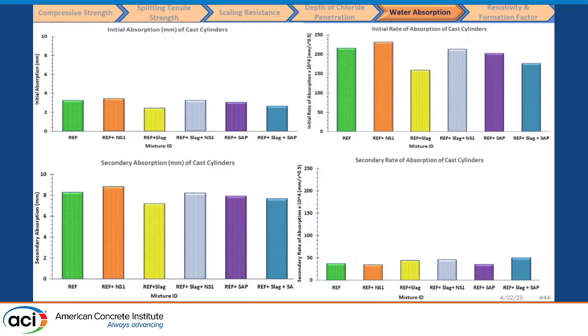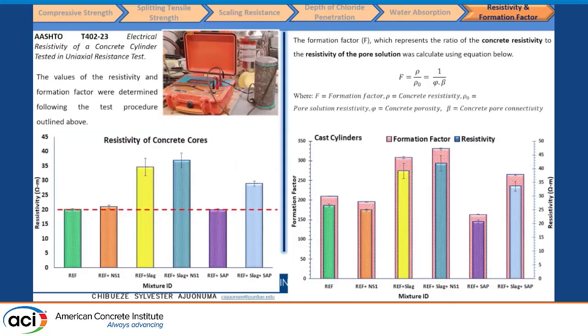And for water absorption, we noticed a gradual reduction. We noticed a reduction in both initial and final water absorption with the addition of 30% slag cement in the mix. And finally, we look at the resistivity, which correlates with the depth of chloride penetration. We noticed the addition of SAP increases the resistivity and the formation factor for the mixes, which shows the refinement of the microstructure. It helps to reduce the permeability, which translates to higher durability for the concrete mixes.